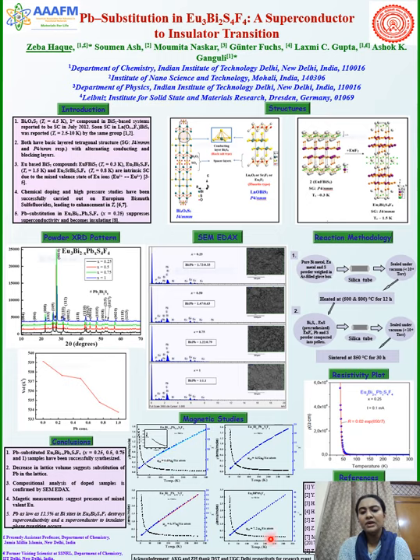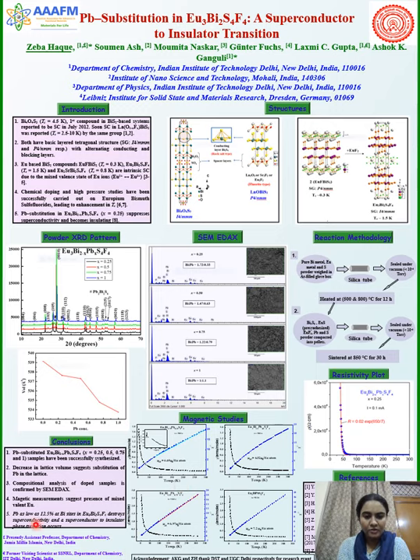All remaining samples with higher lead content also show paramagnetic behavior with the magnetic moment varying by ±0.2 to 0.5 Bohr magneton. In conclusion, lead doping in Eu3Bi2S4F4 has been successfully carried out, as demonstrated by shrinkage of the unit cell volume and confirmed by SEM-EDAX.